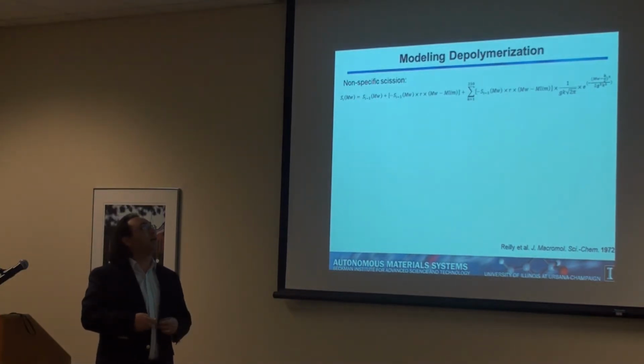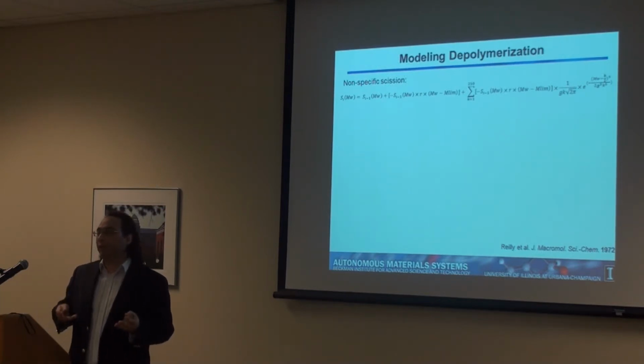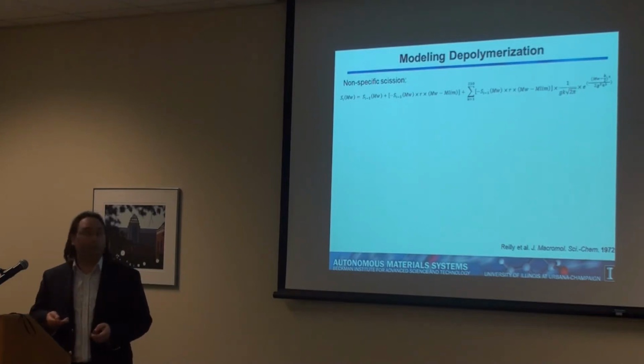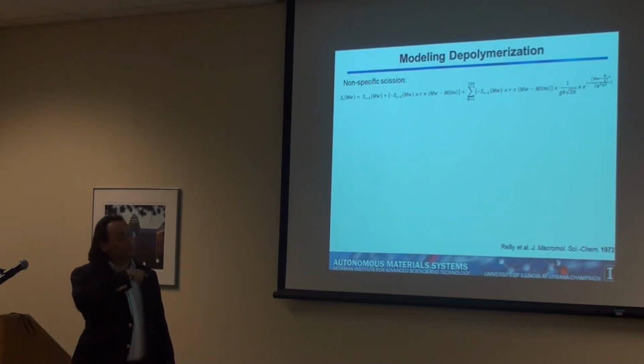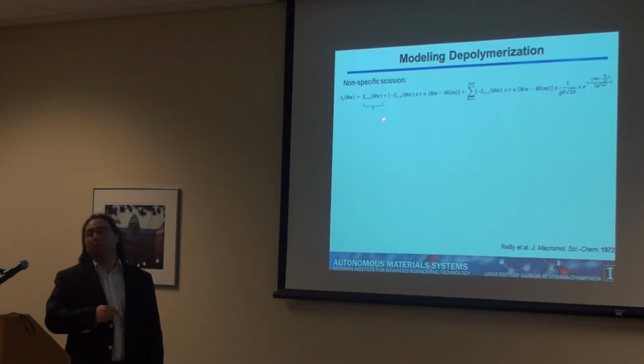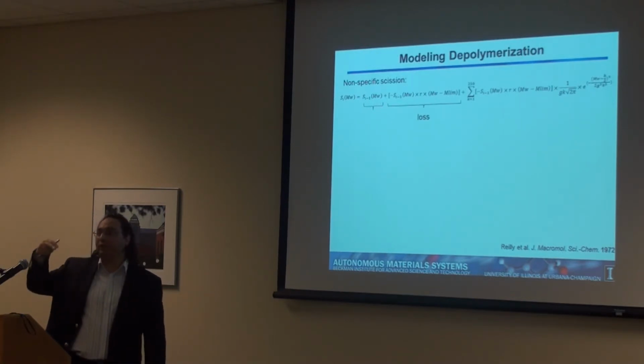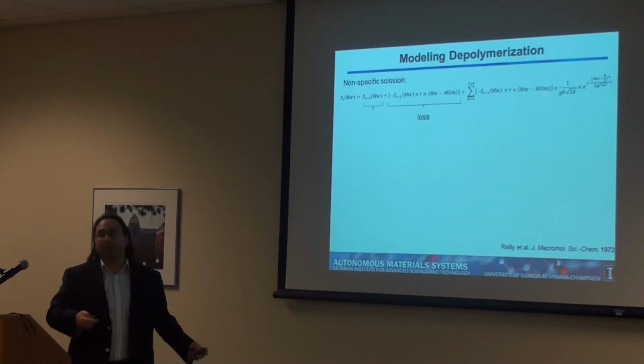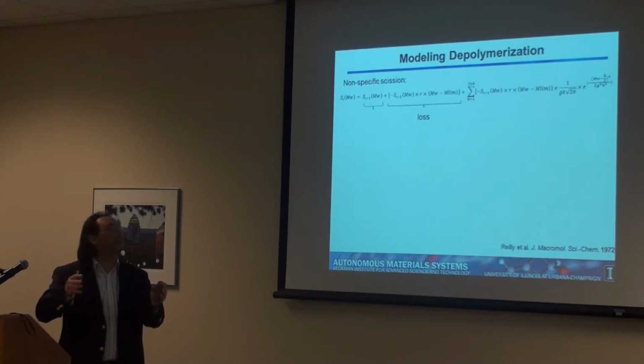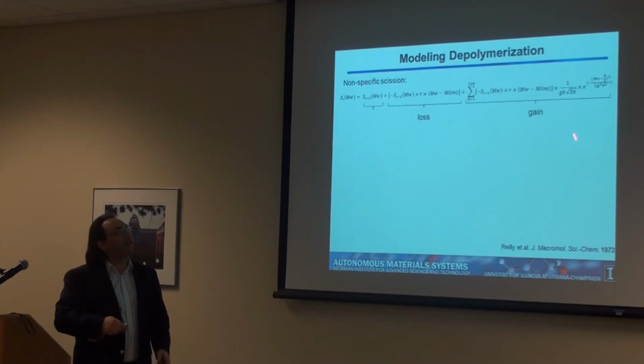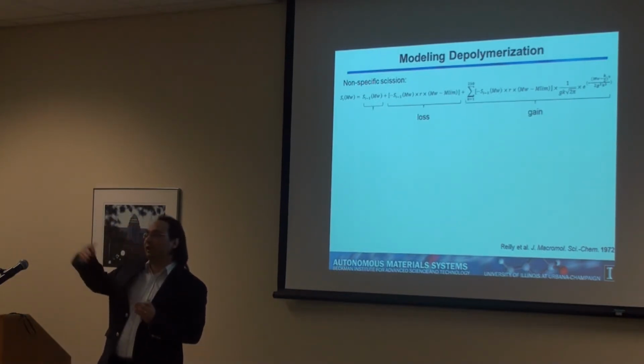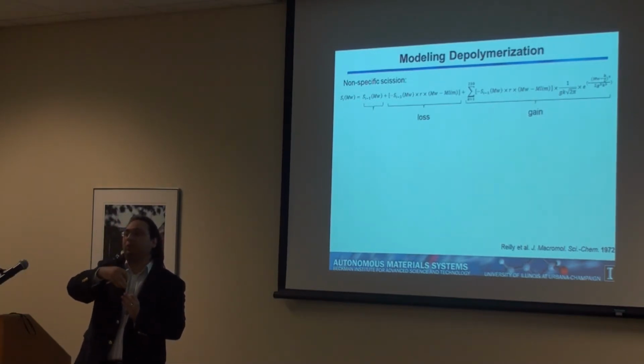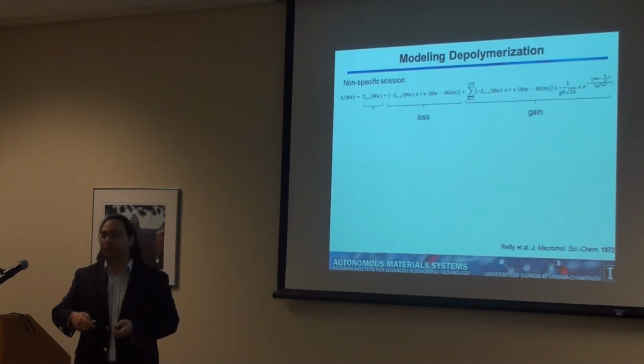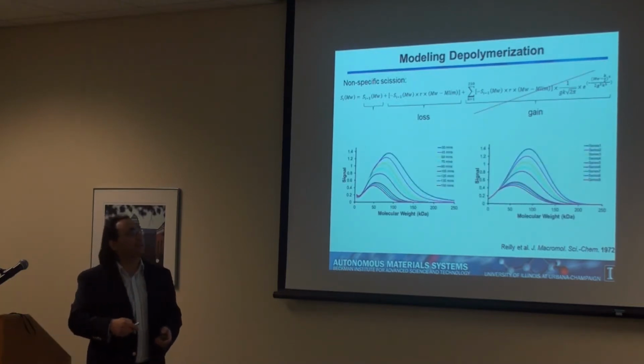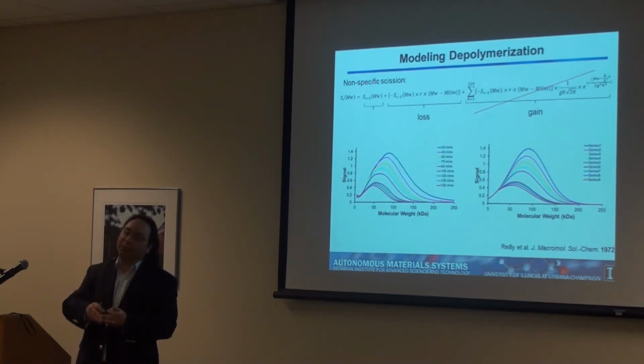So we decided to model this. There are several mathematical models for the change of the molecular weight distribution of the polymer as a consequence of degradation. This is one model that we've been using for different cases. Basically, it says that the concentration for each molecular weight is made from the previous one. Then you lose some of it in each step, which depends on a certain rate and the distance of the size of the polymer to the limiting molecular weight for degradation. And then you have a gain factor, which is basically the chance that a higher molecular weight polymer is going to break and give exactly that molecular weight. So you have a decrease factor, and then a gain factor. And we said, okay, for the depolymerization, what we have to do is take this one out, because we are not gaining any new polymer, since when it breaks, it completely depolymerizes.